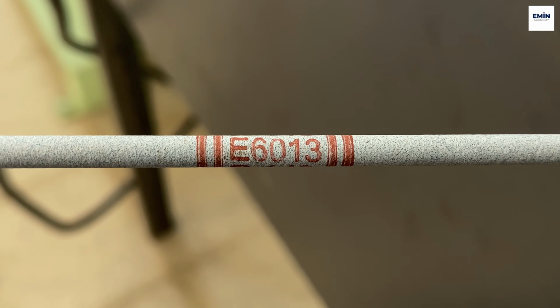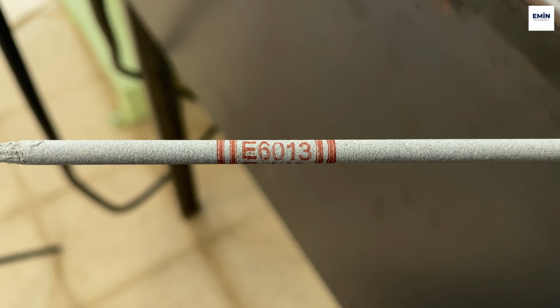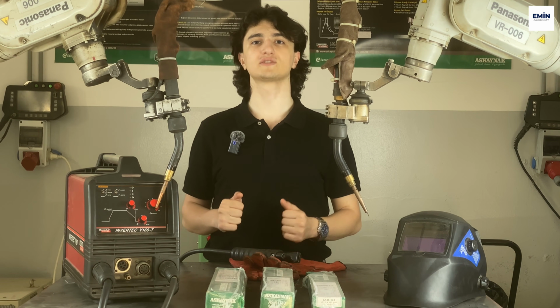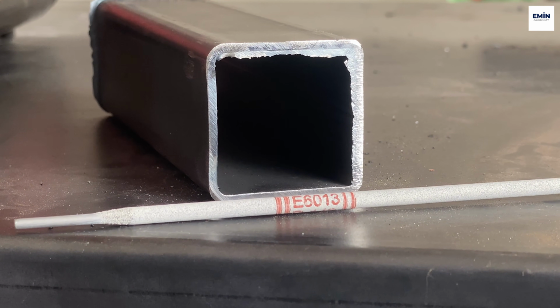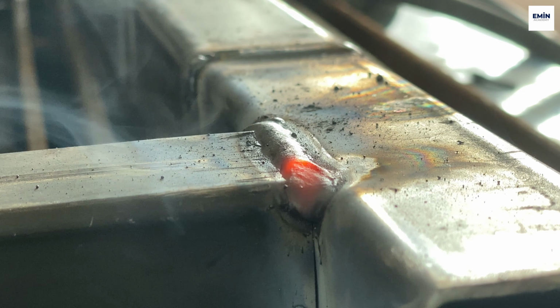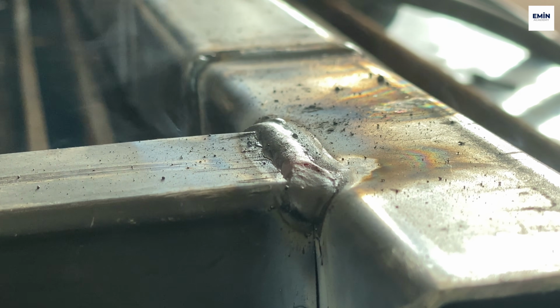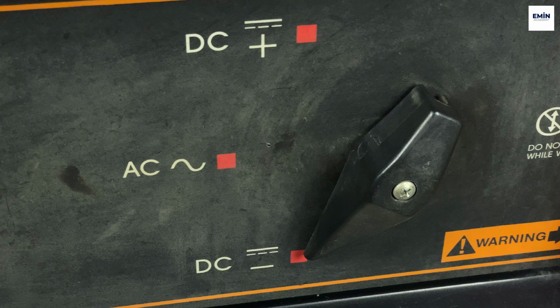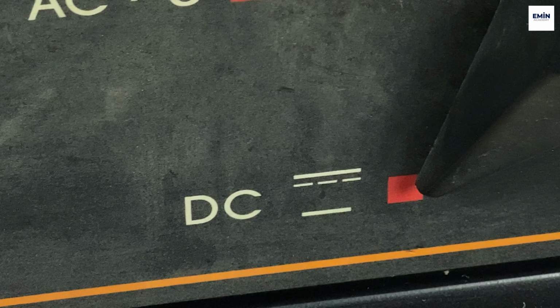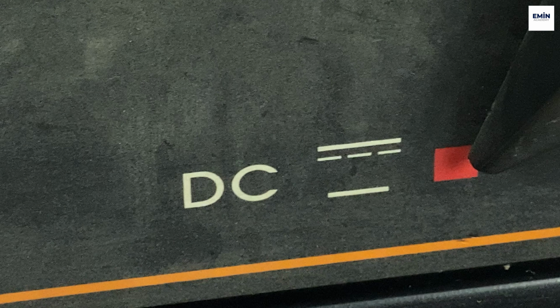3. Rutile-coated electrode. The E6013 electrode is an example of this. The arc is soft, it has low spatter, and the slag is easy to clean. It's generally used on thin materials for repair work and in general fabrication welding. It's suitable for alternating current, direct current electrode positive and direct current electrode negative polarity.